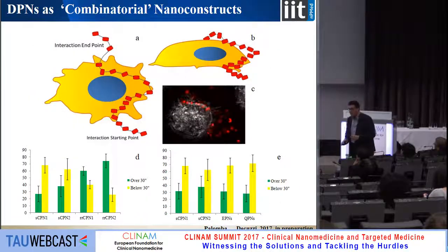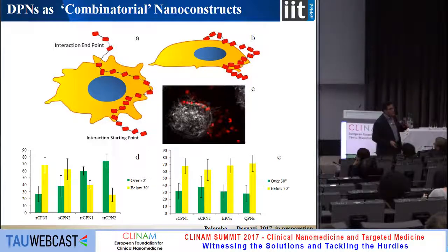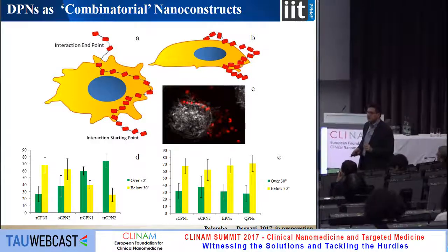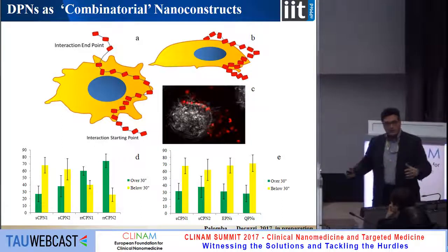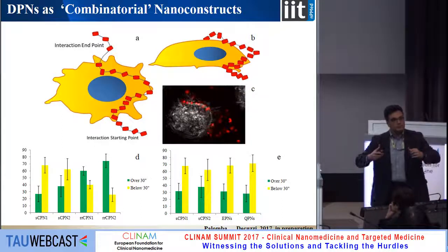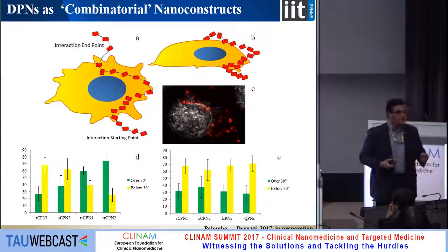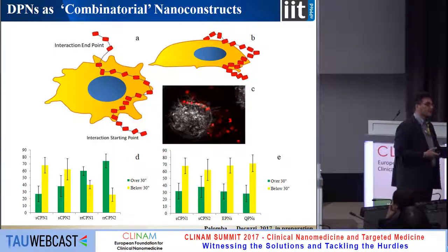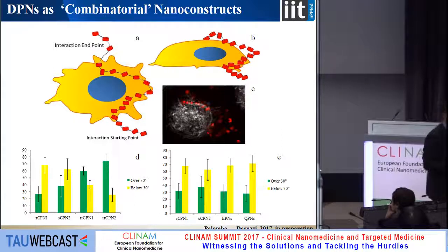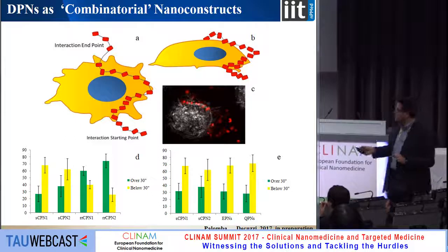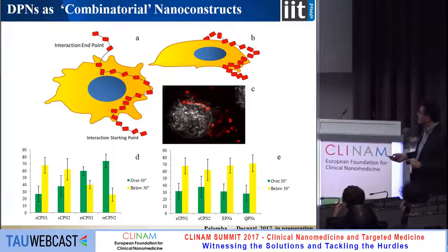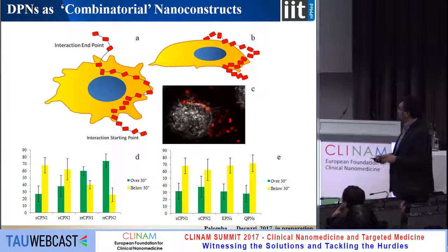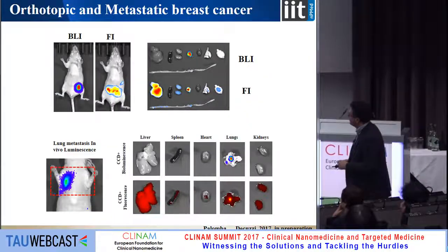But one thing that is emerging is that the soft particles actually spend less time in the vicinity of the bone marrow-derived monocytes. They get closer, but they cannot be engulfed by them. With the rigid particles, that's exactly what is happening, on a much shorter time period. So we're still working on this, because there is a lot that can be done in trying to avoid the sequestration by the RES system.